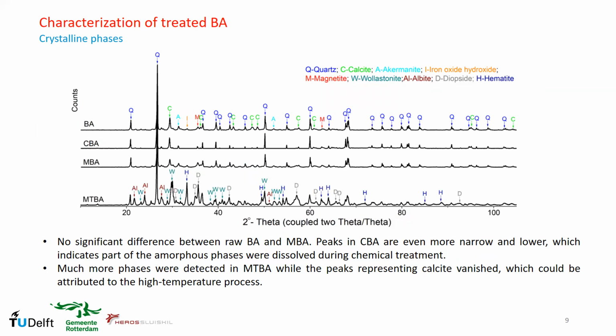For the characterization of the treated bottom ash samples, first the crystalline phases by XRD. Here we found that there is no significant difference between the bottom ash and the MBA. The peaks in the CBA samples are even narrower and lower, which indicates that part of the amorphous phases were dissolved during the chemical treatment. And after the thermal treatment, we found there are more phases, while the peaks corresponding to calcite vanished, which could be attributed to the high temperature process.